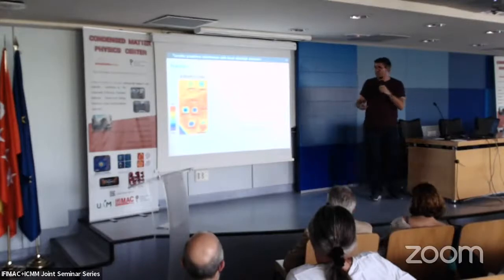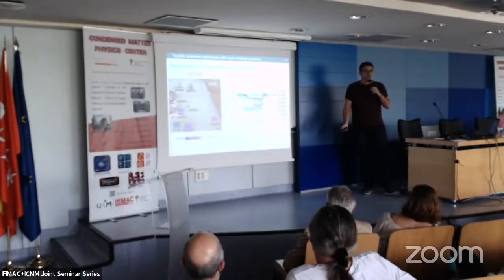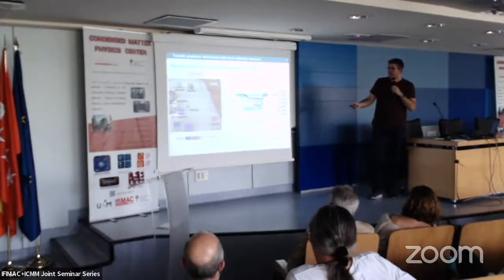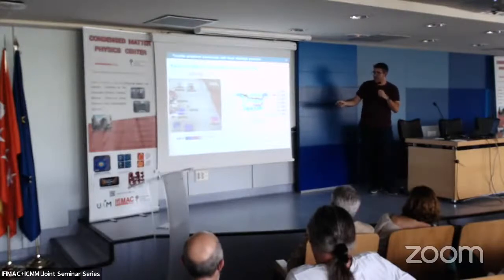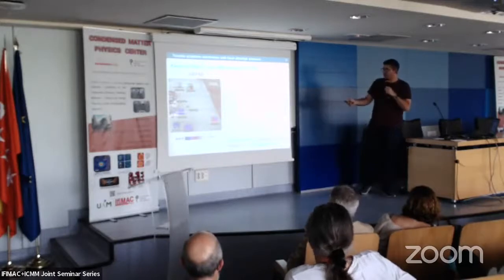But to get more quantitative data on the doping level, we also performed scanning Kelvin probe microscopy imaging. This is a special mode of AFM, an electrical mode in which we can get information on the contact potential difference on our surface. If we now take images of these same modified areas, you can see how again the contrast is changing. If we plot, for example, profiles of this area, we can see that at 16 gigapascals there is no change in the contact potential difference, but as we increase it to 20, 25, and so on, this contrast is changing. And this contact potential difference variation we can directly relate to the change in the Fermi energy level. So we can control the Fermi energy level very precisely with the pressure.